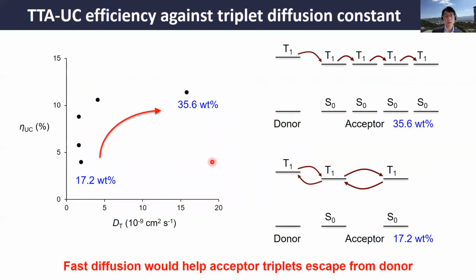So to get deeper insight, we estimated the apparent diffusion constant from other upconversion parameters like threshold excitation intensity and triplet lifetime. So this is not a monotonic, simple relationship. We cannot explain everything from the diffusion constant, but we consider that the increase of the diffusion constant partially contributes to this improvement of upconversion efficiency.